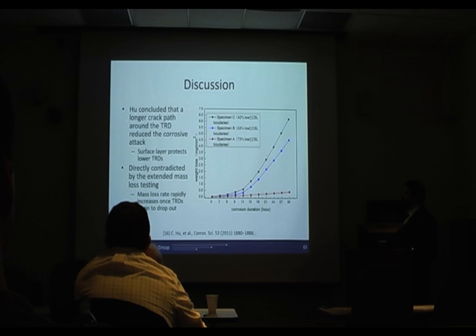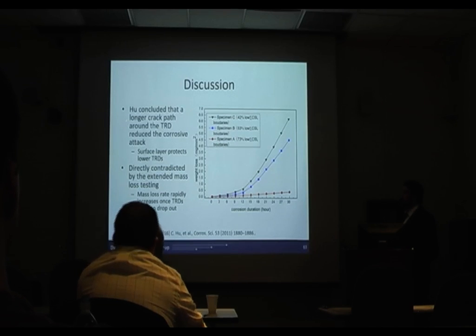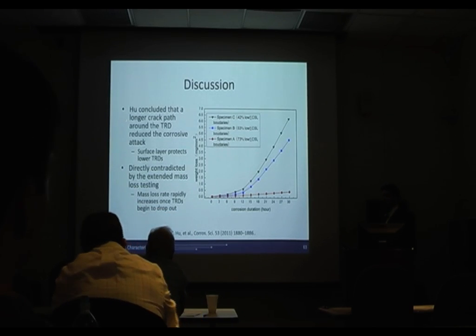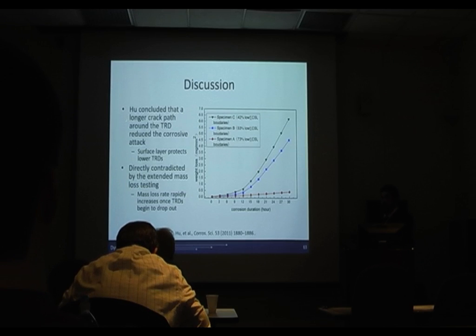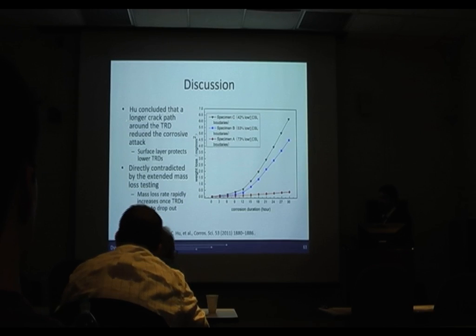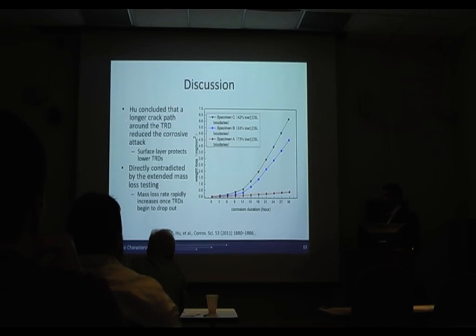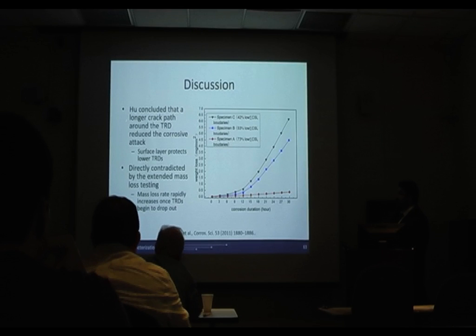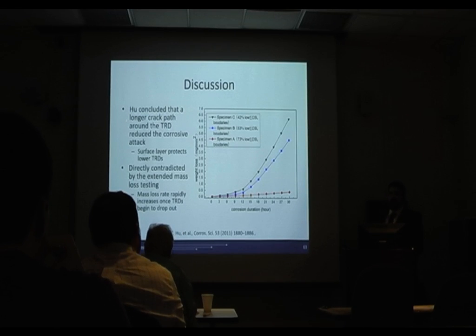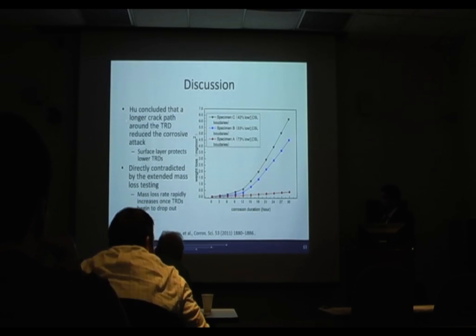This was actually a slightly different environment as well. It wasn't the standard ASTM 262. But what he was hypothesizing was that the surface layer of the TRDs is protecting the lower TRDs. Since they're relatively large, he hypothesized that it would take a lot longer for the cracks to get around behind them and expose the grain boundaries underneath. However, this is directly contradicted by what I've observed in the extended mass loss testing, because I'm noting a rapid increase in the mass loss as soon as you start dropping TRDs.